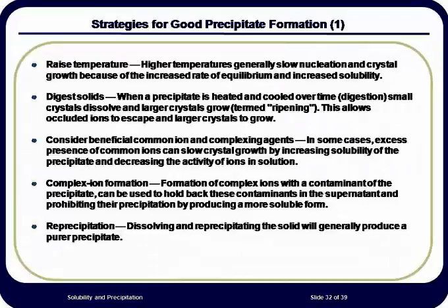Another technique is to add a complexing agent that will not affect the precipitate, but will affect the solubility of a specific contaminant. This was mentioned earlier in the case of uranium separation from thorium in the iron hydroxide solution. Air-saturated ammonia solution is also saturated with carbon dioxide. The carbon dioxide becomes carbonate in basic ammoniacal solutions and strongly complexes with uranium, preventing its precipitation. However, the carbonate does not complex with the thorium.